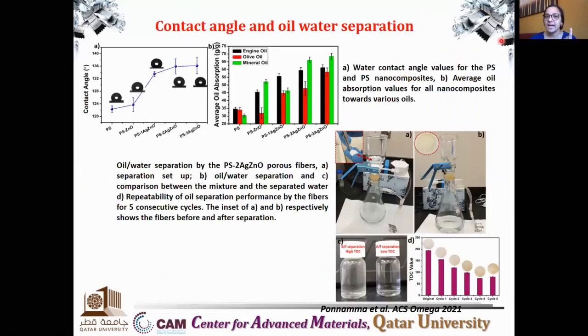And these are the contact angle and oil water separation results. Contact angle again shows that PS silver doped zinc oxide has a high contact angle when compared to polystyrene and polystyrene zinc oxide. And we tested the oil water separation capacity with three different oils: engine oil, olive oil, and mineral oil. And we found different average oil absorption rates for all these oils. But in this case, you can see that the best performance was obtained for the mineral oil. So this can be due to the density or the viscosity influence.